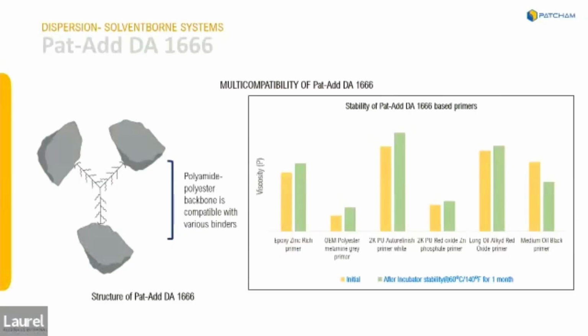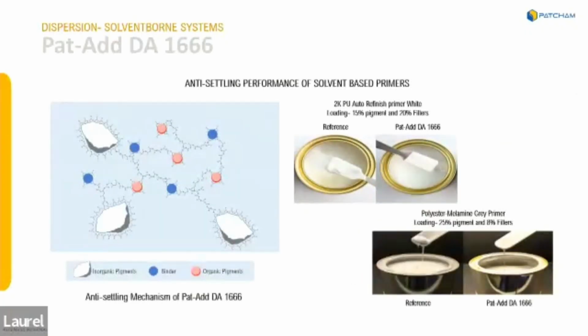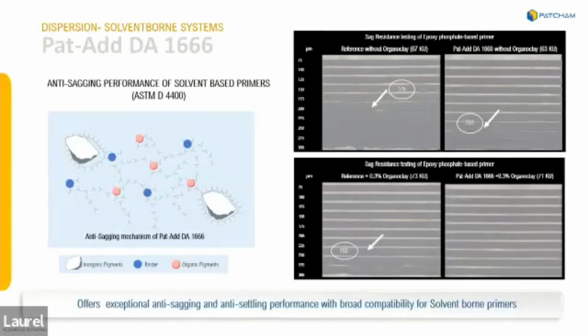Pictorially, it's multifunctional, so it can capture actually more than one particular substrate. It has the capability of hanging on to multiple groups, what we describe as controlled flocculation. Not true flocculation because there's no contact between these particles. There's a polymer between them. That's the dispersion stabilizing additive that is capable of self-structuring to provide interesting rheological properties to your coating, to prevent the settling of dense particulates that we put into the coating system, improve sag resistance without affecting its viscosity. We can actually show higher sag resistance in a lower viscosity than the reference.